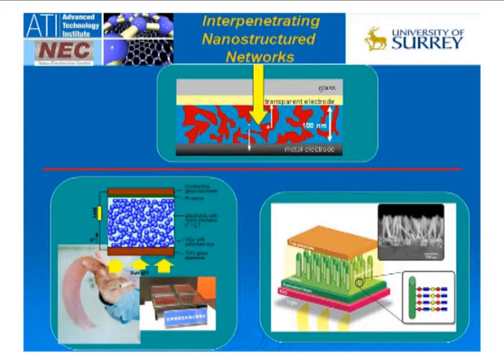So similar concepts have been used when it comes to, say, dye-synthesized solar cells or the Grätzel cells. And in the case of Grätzel cells, once more, you can start looking at titanium dioxide. And these are very good photocatalytic materials that enhance the redox process. And again, nanostructured materials there can allow better absorption of the photons that are hitting it and thereby allow the charge transfer. So the ideal structure many people are aiming at is actually shown in this diagram.